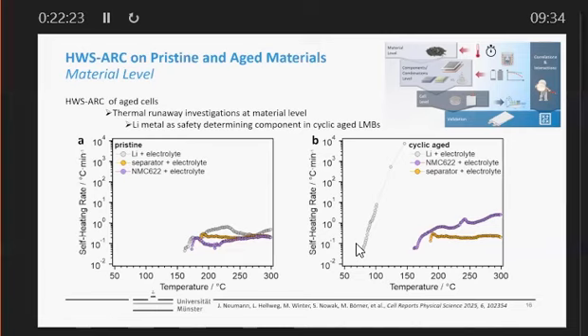For cyclic aged, we see that for the NMC, electrolyte and separator, everything remains more or less the same. So it's again beyond 150 degrees C, but the lithium metal moves down, the onset moves to 80 degrees C, because we have created high surface area lithium. So a typical safety test at 90 degrees C would already be beyond the scope of this lithium metal battery.